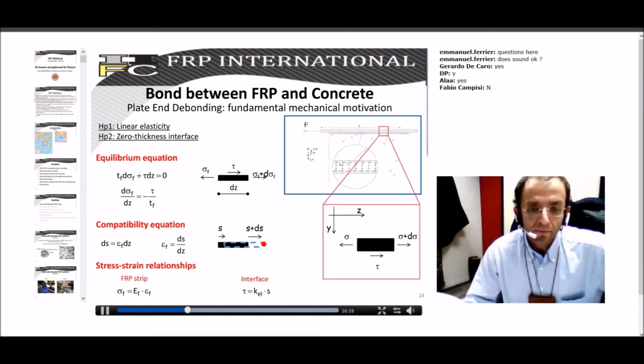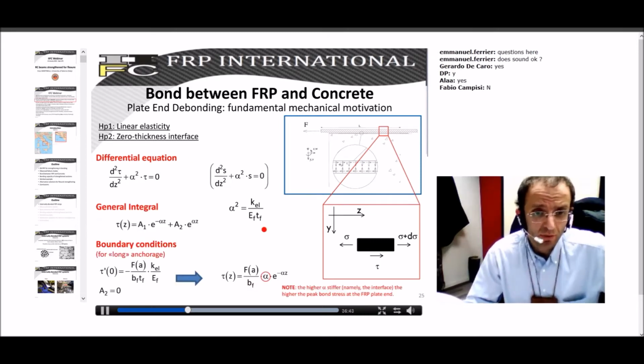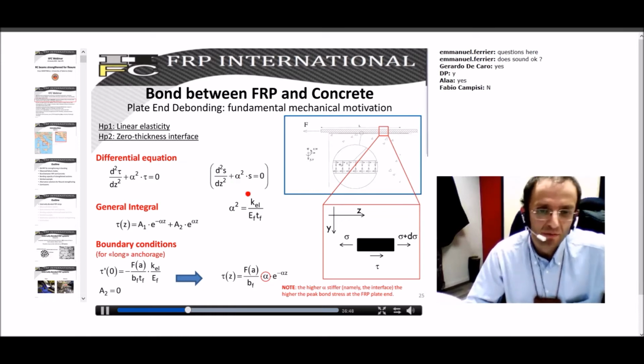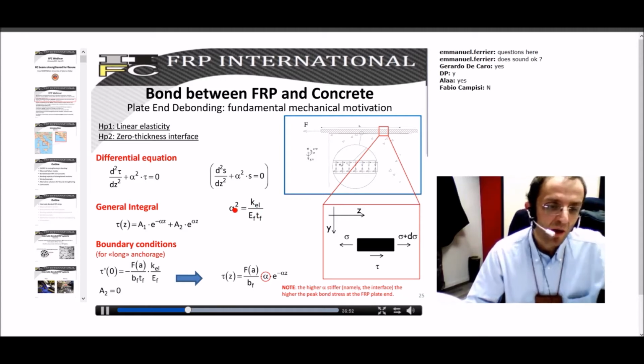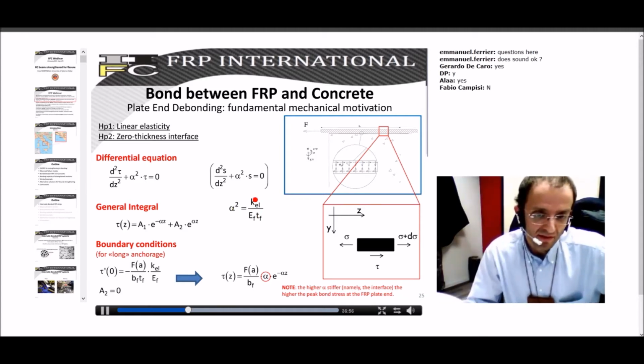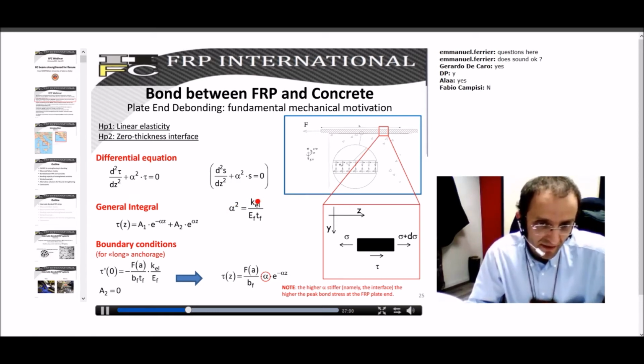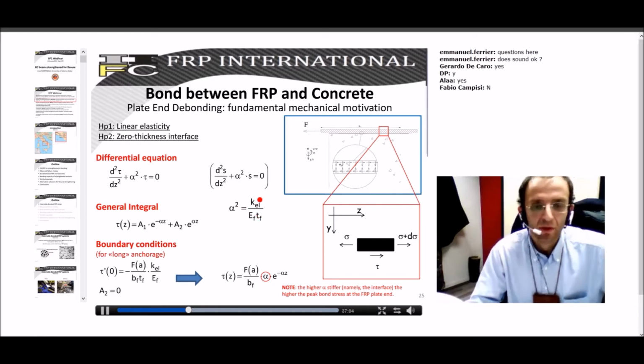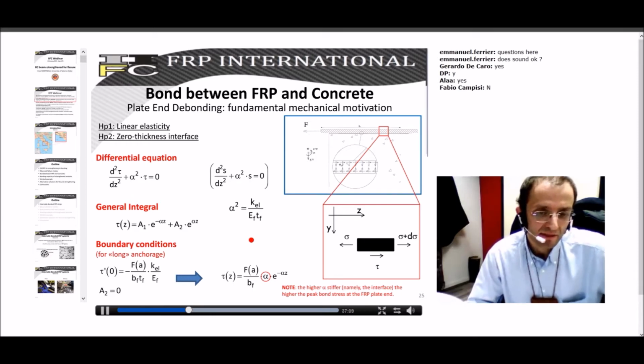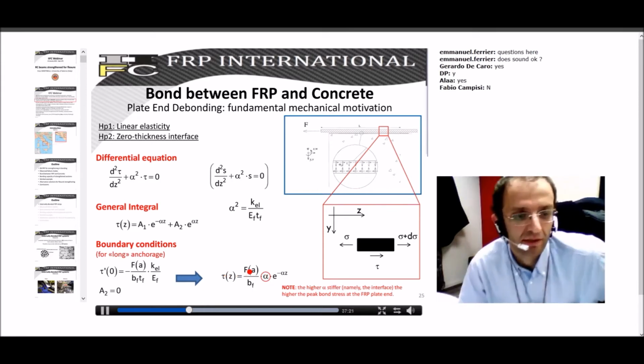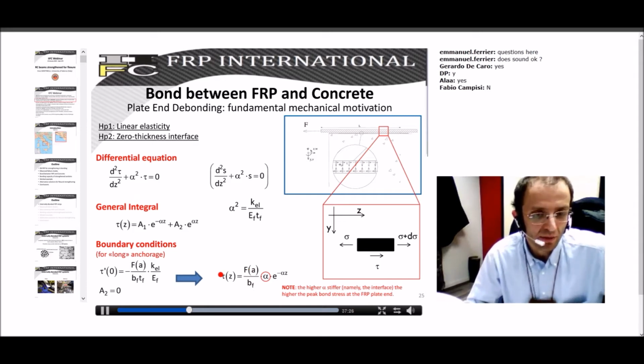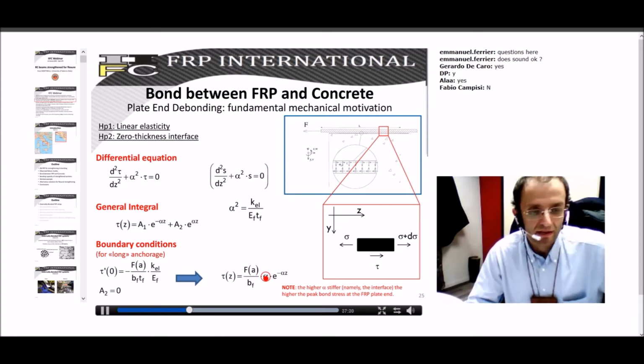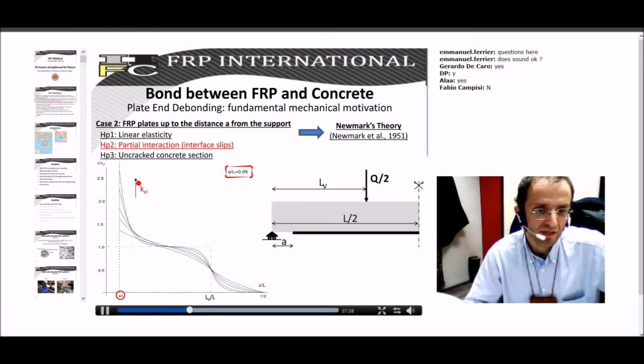Okay. So if you put all this together, what you get is a differential equation governed by the parameter alpha, which is an interaction parameter, whose value is as high as the interface is stiff. As you see here, alpha squared is as high as the interface is stiff, or as low as the FRP is stiff. So this is an interaction parameter which controls the shape of the distribution of the interfacial tau throughout this interface. So tau depends on alpha. If you have a very stiff interface, you will have a tau with a very high peak value. If you have a soft interface, you have a tau which is almost uniform. So we'll see some solutions here. So you see here K elastic.